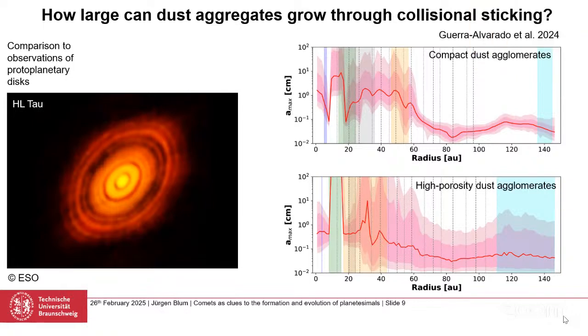And they applied, of course, there's lots of modeling to interpret the dust size. They adopted 2 models, agglomerates that are compact and agglomerates that are very fluffy. And you are seeing here's again a centimeter in the inner 40, 50 AU centimeters, in the outer is millimeters or so. And here it's slightly different, very different in this particular ring here. I don't know which model is the best one, but give or take, they are the pebbles.